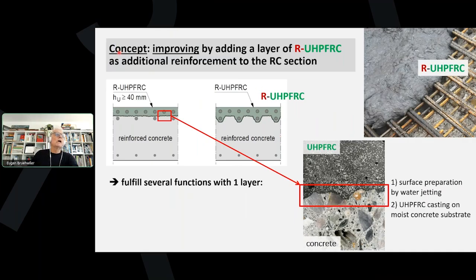Now, we have understood that the concept is to improve reinforced concrete by adding a layer of R-UHPFRC as an additional reinforcement to the reinforced concrete section. So we have such composite elements. And then, of course, the basic question is, how can we get composite action here? What happens at the interface? Now, it is very important that we prepare the reinforced concrete substrate, and water jetting is the very best method. And it's important to have a wet, moist concrete substrate surface when the fresh UHPFRC is cast on top of it.